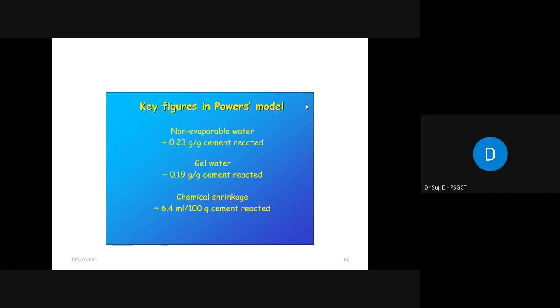So according to Power's measurement, chemically combined water, which is also called non-evaporable water, is 0.23 grams of water bound per gram of cement during hydration, right? This water is called chemically bound water, and it is non-evaporable also. So you can evaporate this water only if you heat the system up to 105 degrees centigrade. Until then, this water will not be taken out, right? So it is an integral part of the structure of the gel or CSH gel, right? So on the surface of the gel solid, CSH is a hydrated silicate, calcium silicate hydrate gel.